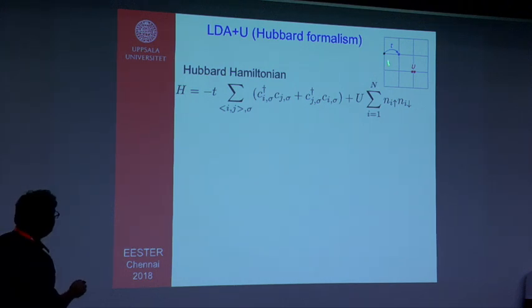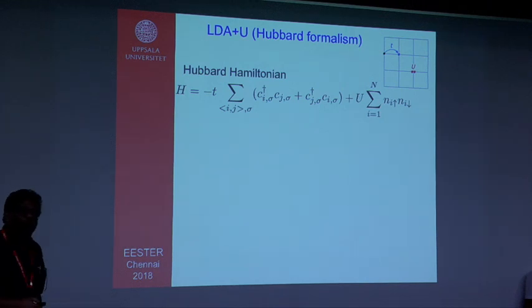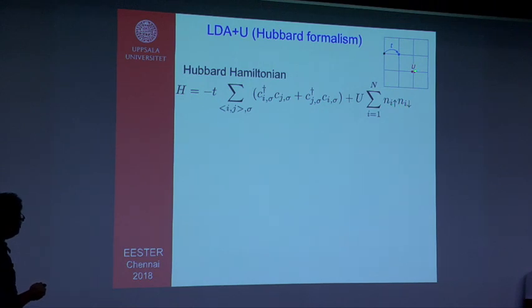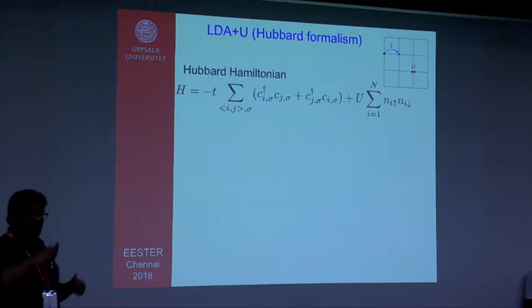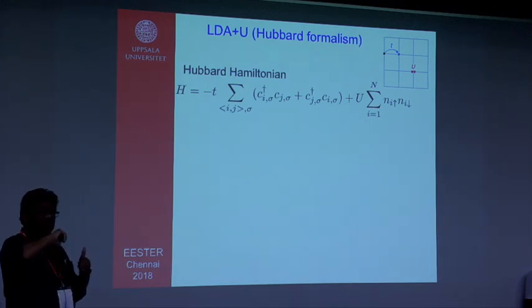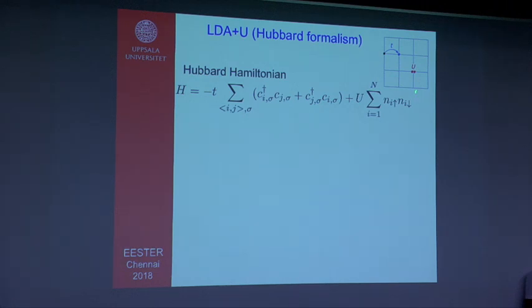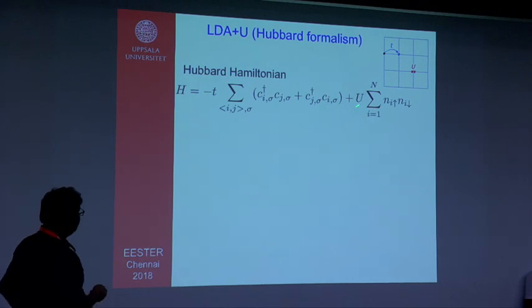If you look at this picture on the right side, this electron is hopping from one site to the other with a kinetic energy term T, the hopping term, which is negative here. But you have a repulsive term here, which is given by the Coulomb repulsion. If you look carefully, you see that this is an on-site Coulomb repulsion. That means when an electron comes to a site and finds another electron there with an opposite spin, because the Pauli exclusion principle has to be maintained, then these two electrons face a very strong Coulomb repulsion, and that is given by this U here.